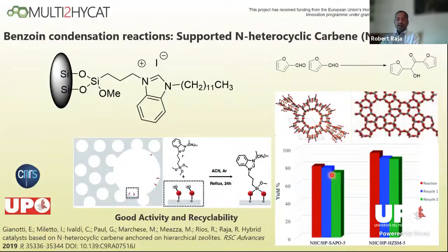synthetic strategy. So through the anchoring of this benzimidazole moiety to these silanol groups within the hierarchical structures, we see this enhanced conversion, but we also see that the ZSM5 hierarchical structure is far more stable and can be recycled quite effectively, paving the way for the industrial validation of these types of catalysts for the benzoin condensation reaction.